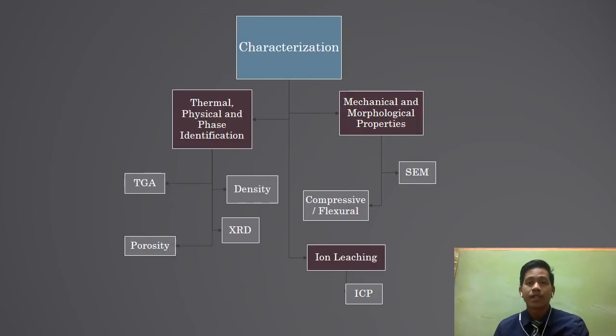For the characterization, the sintered samples will be subjected to evaluation of mechanical and morphological properties using a universal testing machine and field emission scanning electron microscope. The crosshead speed during the mechanical testing will be 1 mm per minute. The strength, elastic modulus, and strain of the sample will be recorded. Meanwhile, identification of phase, thermal, and physical characteristics will be conducted using an X-ray diffractometer, density balance, and thermogravimetric analysis device.